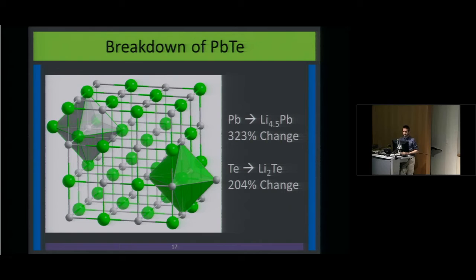One theoretical reason we have is that the two different materials have much different volume changes as they expand. First you insert lithium into the tellurium, which undergoes a 204% volume change. Then you insert it into the lead, which undergoes a 323% volume change. The fact that they're expanding and contracting at different times, with different magnitudes, basically destroys this crystal lattice, and the tellurium and lithium can't recombine into a single crystal structure. However, that doesn't seem to have much impact on performance because we still get really stable cycling. I'm going to be working with Kyle to do more experiments to find out whether this is actually happening and to determine the exact mechanism of this breakdown.